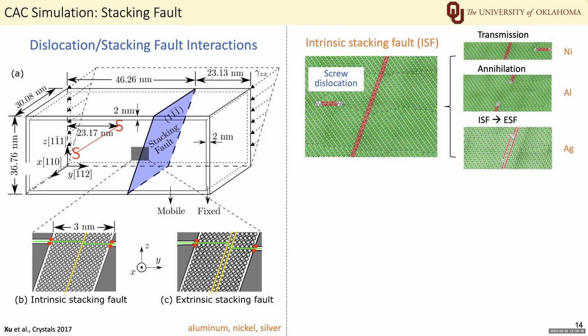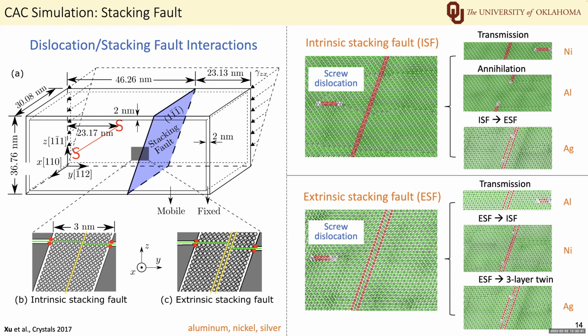For the intrinsic stacking fault, we find that the screw dislocation cuts through it in nickel, annihilates in aluminum, and transforms it into an extrinsic stacking fault in silver. For the extrinsic stacking fault, we find that the screw dislocation cuts through it in aluminum and transforms it into an intrinsic stacking fault in nickel, while transforming it into a three-layer twin in silver. The different interaction modes are due to the different fault energies and their ratios in the three FCC metals.